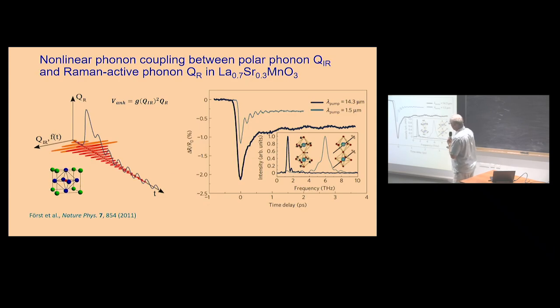In 2011 this paper was published, when they pumped the highest frequency phonon, which is around 17 terahertz, which is just deformation of the oxygen cage in perovskite, lanthanum strontium manganite. And when they measured the change of reflectivity, it is, let's say, a 2% change, which is not huge, but from these oscillations you can calculate the Fourier transform. And you obtain the spectrum from these oscillations.